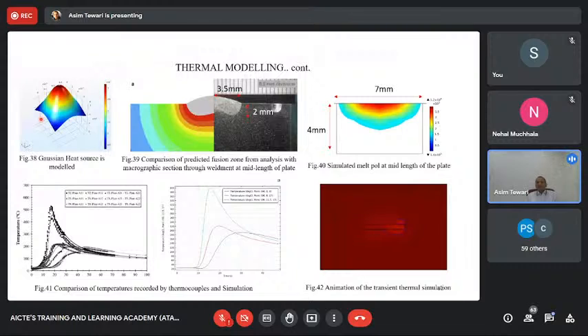In our case, for instance, if we have a laser source, usually a laser source has a Gaussian heat profile, which is what I'm showing you over here. Highest temperature, highest heat per unit area at the center, and as you go further away from the laser heat source, though the spot size could be, let's say, 1 mm or 2 mm, that 2 mm does not have the entire 2 mm as equal heat. You have very high heat at the center. So you need to model that.